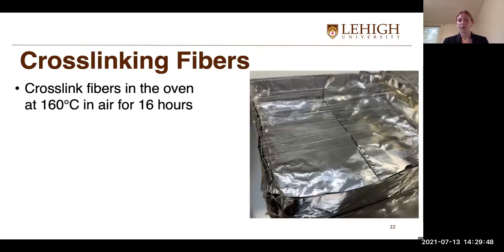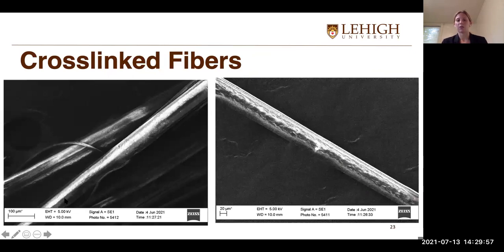So I cross-linked the fibers in the oven, similar to the powder, at 160 degrees Celsius in air for 16 hours. And here are some images, so you can see that the fibers are pretty long and uniform.